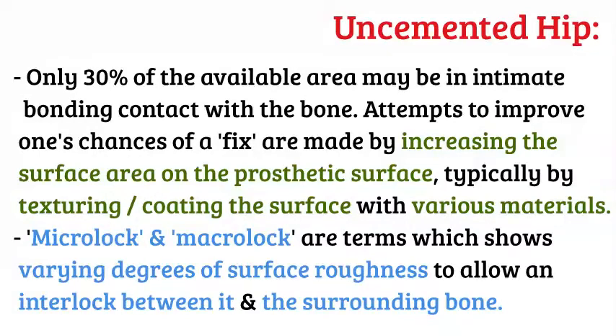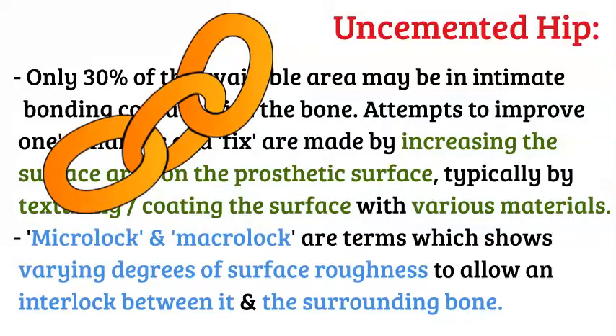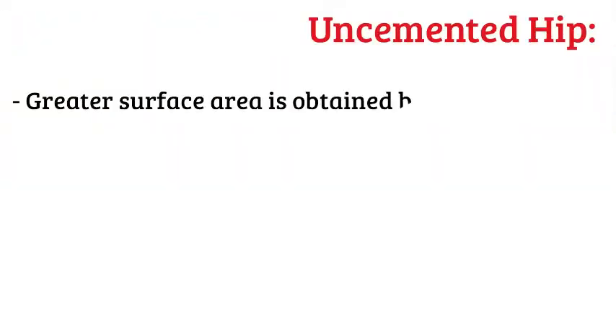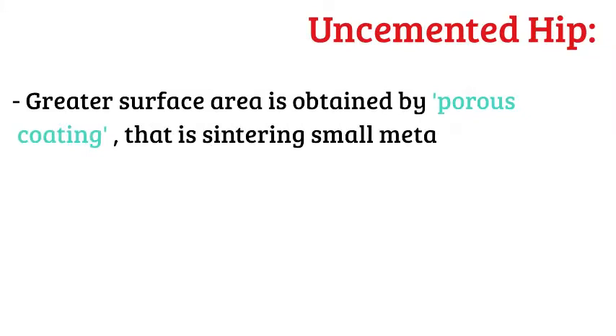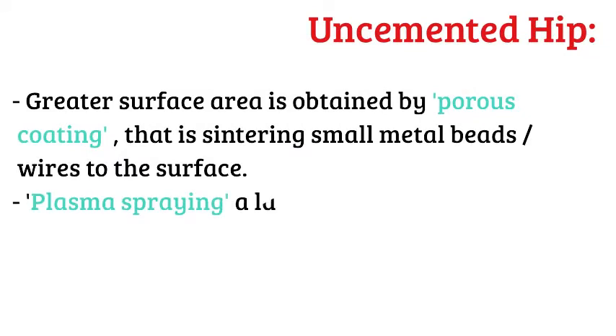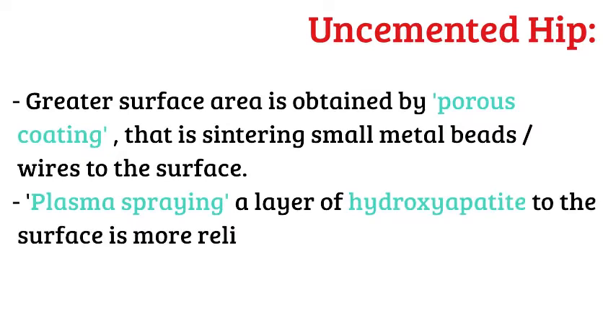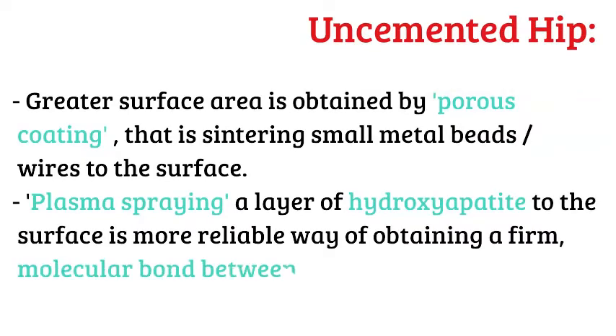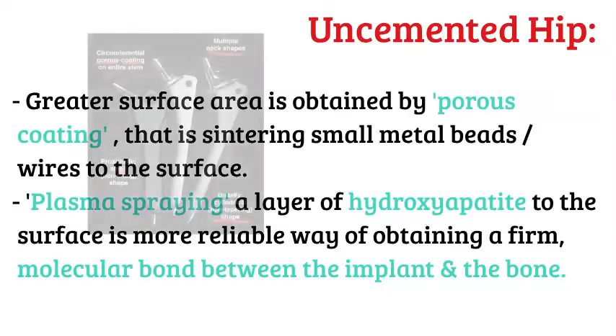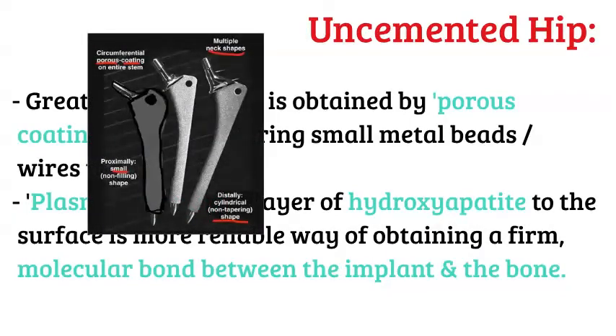Microlock and macrolock are terms which show varying degrees of surface roughness to allow an interlock between it and the surrounding bone. A greater surface area is obtained by porous coating, that is, sintering small metal beads or wires to the surface. Plasma spraying a layer of hydroxyapatite to the surface is a more reliable way of obtaining a firm molecular bond between the implant and the bone.